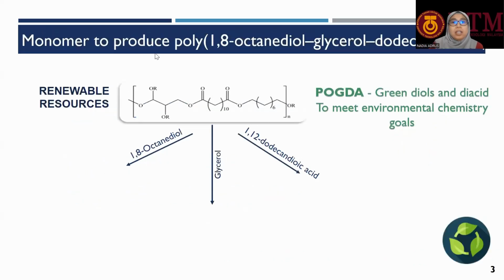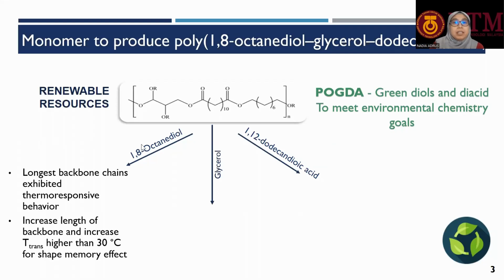So, in our group, we have successfully produced poly(1,8-octanediol-glycerol-dodecanedioic acid), so-called POGDA, because the monomers used to produce this polyester, which are the diols and also the diacid, are from renewable resources. This POGDA is a green diol and diacid base in order to meet the environmental chemistry goals. Specifically, the octanediol here gives the backbone chains and also exhibits thermoresponsive behavior, as the chain can be used to increase the transition temperature higher than 30 degrees Celsius for shape memory effect.